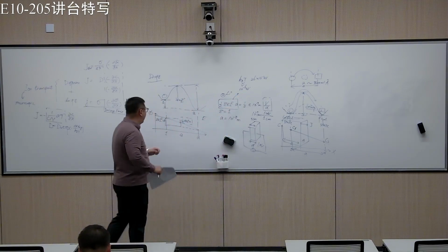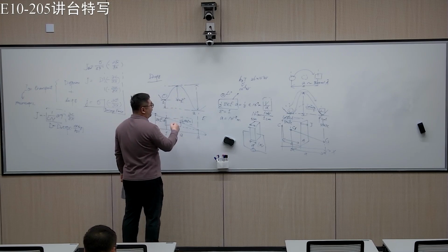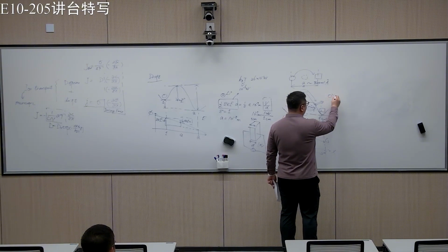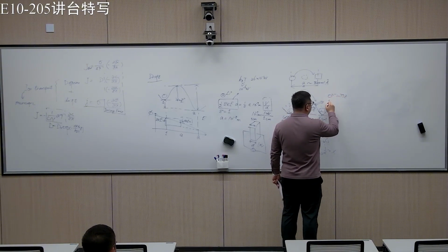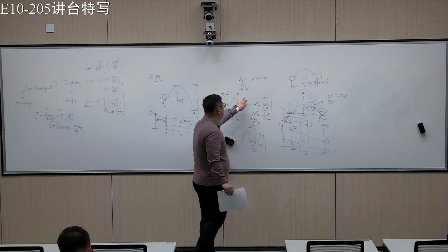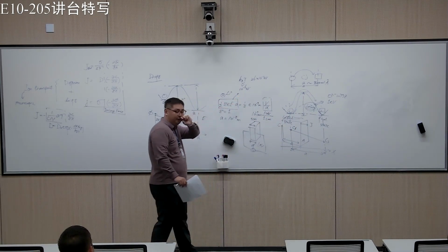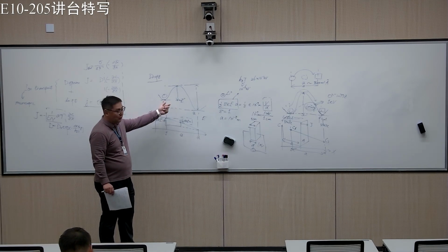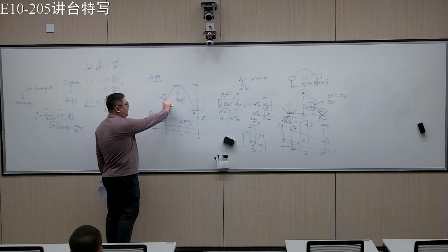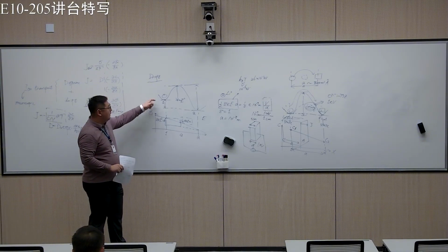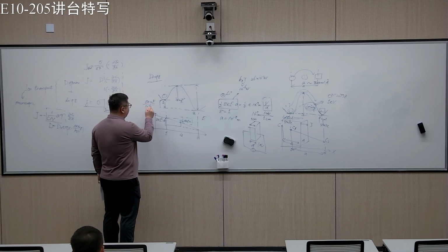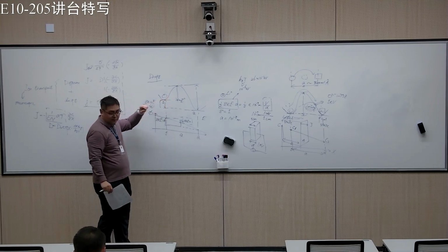And the migration barrier, we say for oxygen in YSZ is something like 1 eV. So that's 10 to the 6 orders of magnitude higher than this one. That's why I'm saying this is really an exaggeration, right? In reality, you can see only a tiny bit of difference in this case. It's only 10 to the minus 6 eV, so it's tiny compared to this one.